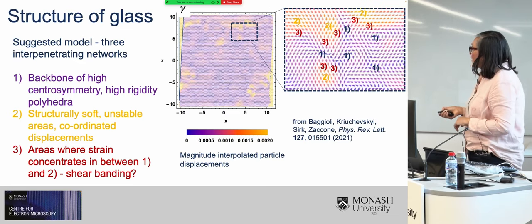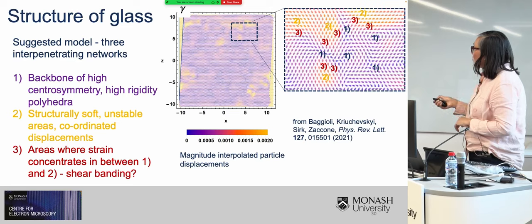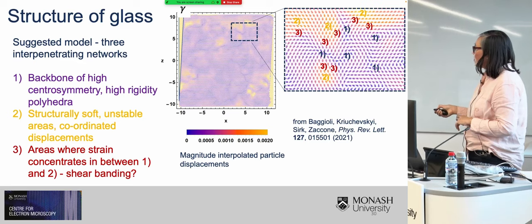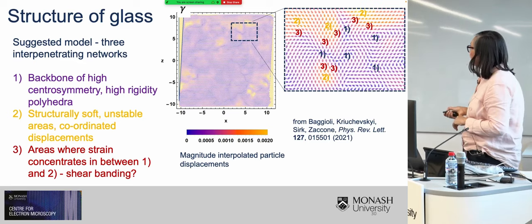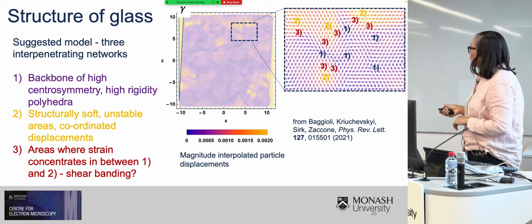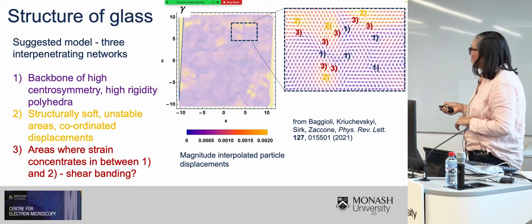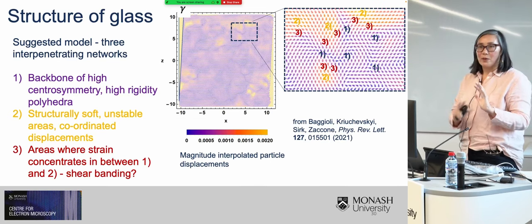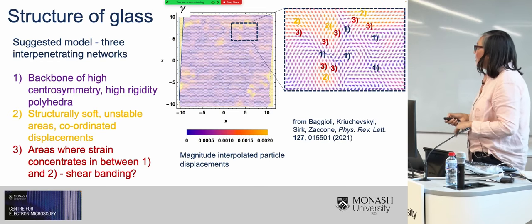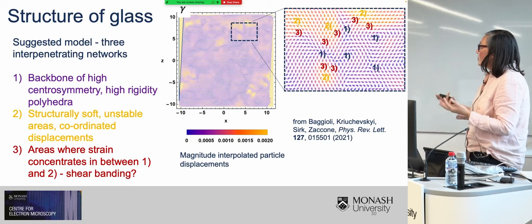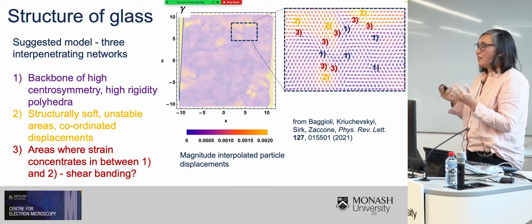And so here I'm showing a model glass which has been strained, and this is the interpolated displacement field in that glass. So here you can see the colour scale that shows the magnitude of the displacements. And so based upon this model and also from staring at the maps that I've produced in my measurements, I'm suggesting this model of a glass, which consists of three interpenetrating networks.